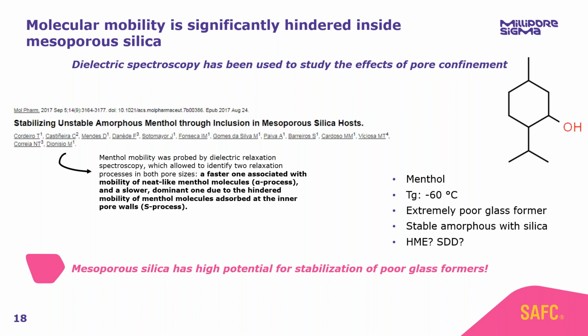And what the researchers found in this study is that when you confine menthol in that 6 nanometer pore environment, you have a substantial reduction in alpha relaxation. Alpha relaxation is one of the critical molecular mobilities along the path to recrystallization. So this molecule is totally hindered in space. It can't move around much. It can't recrystallize. They also observed a substantial, almost complete reduction in beta relaxation, Johari-Goldstein relaxation, sometimes referred to. So both alpha and beta relaxation, alpha and beta mobility, substantially hindered inside that 6 nanometer pore.